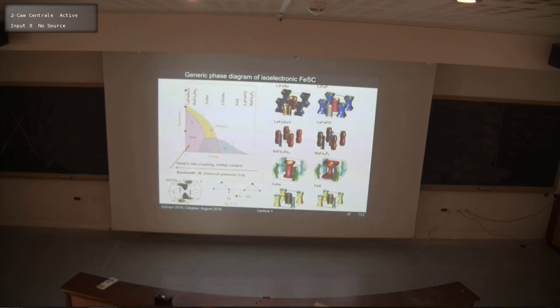Now, when you have a magnetically ordered state, you also expect the Fermi surface to reconstruct due to the new Brillouin zone, and this is what is found in experiments in barium-122 in the magnetic state. Now you have all this reconstruction due to magnetism.